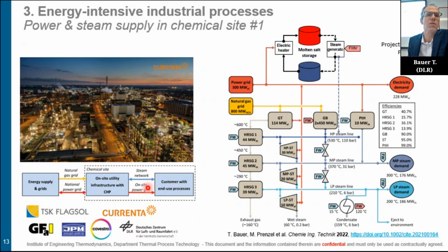We didn't look into the processes. We looked only at the generation. So on the right-hand side here, you can see the generation, the different components. There are gas turbines, gas boilers, waste heat recovery, steam turbines, and so on. And then we checked different storage options. We looked at regenerator type storage, PCM storage, and also a bit at thermochemical storage, Ruths storage, but also molten salt storage. We also looked at different integration points. And the best solution we came up with was to use electricity to charge the storage, use molten salt storage, and then inject high pressure steam here in the line. In this way, we can generate electricity and steam, and we have almost 100% utilization on the discharge.